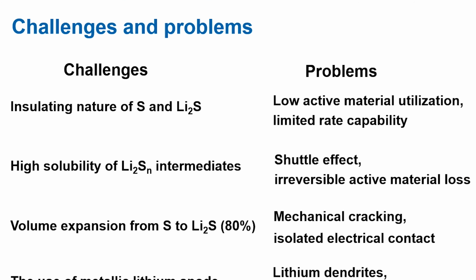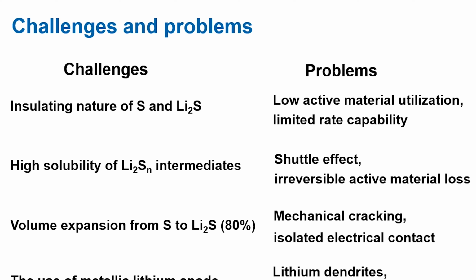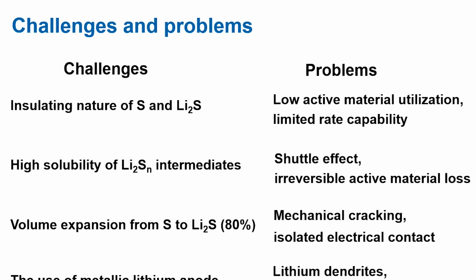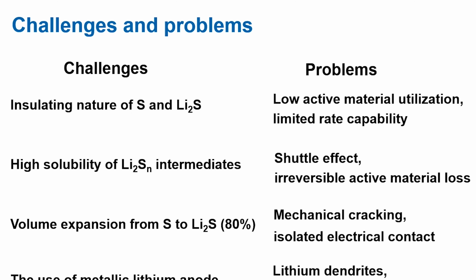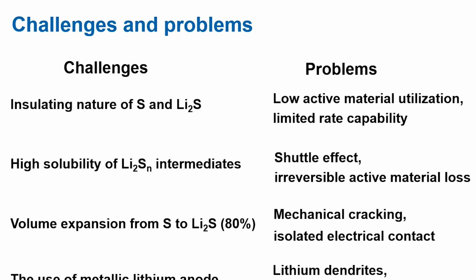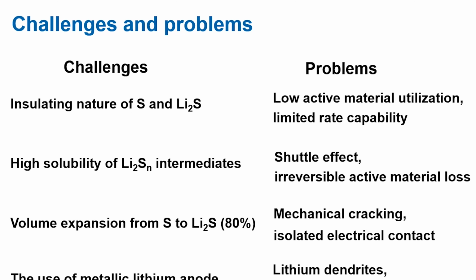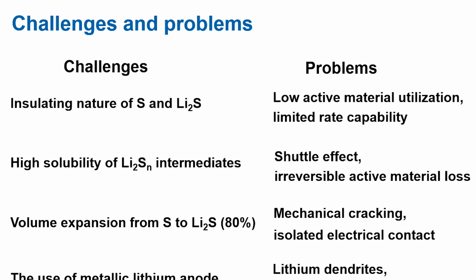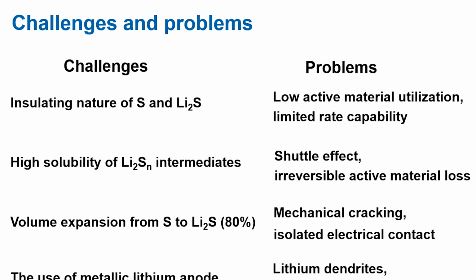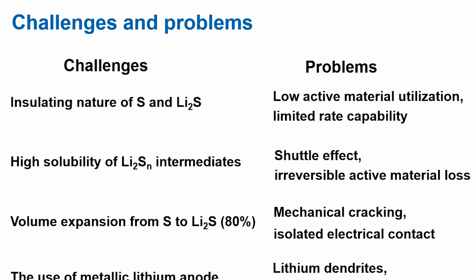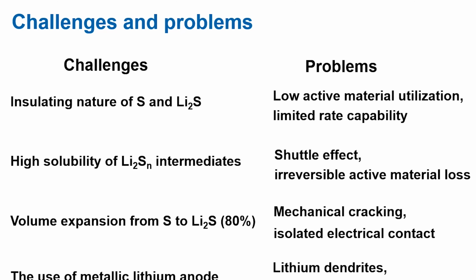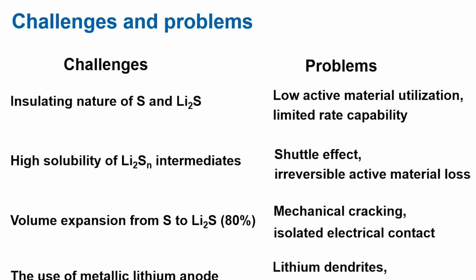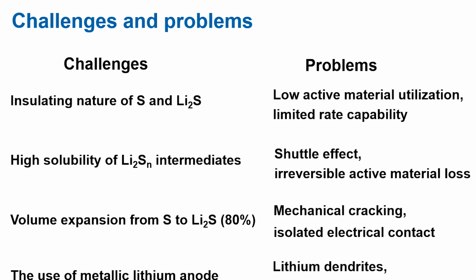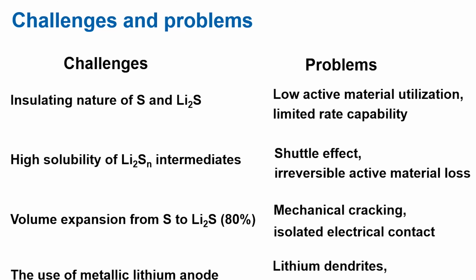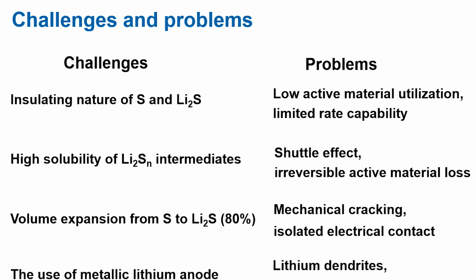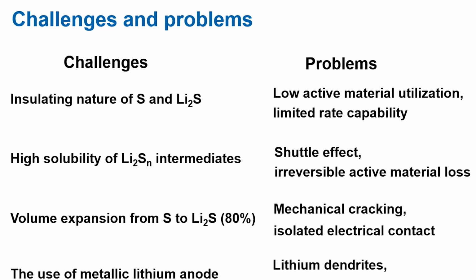However, lithium sulfur batteries also have some challenges and problems. First is the insulating nature of sulfur and lithium sulfide, and this will lead to low active material utilization. Second is the high solubility of polysulfide intermediates, and this will cause shuttle effect and very severe active material loss. Third is the volume expansion from sulfur to lithium sulfide, and this will lead to the mechanical cracking of the electrode. And finally, the use of metallic lithium anode will cause the growth of lithium dendrites and lead to safety issues.